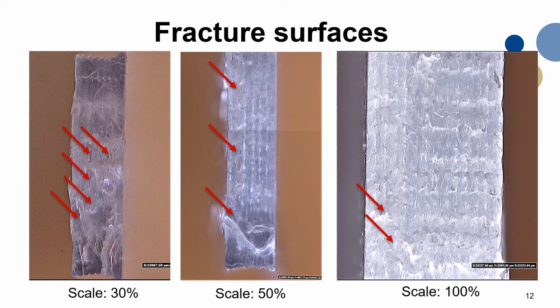And this is how the fracture surface looks under the microscope. As you can see, with the increase of the scale, there's a tendency to have fewer defects and voids on the surface.